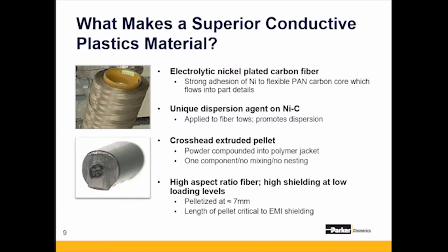Okay, so Ben, what is the specific material used and why does the pultrusion process matter? Yeah, it's a good question, Sierra. We use a nickel-plated carbon fiber, as you can see here on the slide. And the pultrusion process leads to a uniform fiber dispersion throughout the part. Because each pellet not only has the same amount of fiber, but is actually the same size, all the final parts will have a very consistent conductive composition.